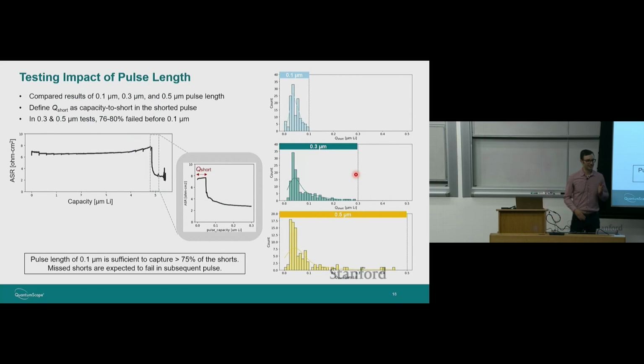I'll do one quick digression here into ensuring that we've tested the validity of our test. One question that we've gotten sometimes is, are you applying this current density for a long enough time to cause a failure, if there is going to be a failure, or are we just doing the test too quickly? Imagine you bend a material very quickly, it'll break at some point. Will that break happen at an earlier or later point than if you bend the material slowly? So that's what we wanted to validate for ourselves, to make sure we're performing a valid test. If we applied current for a longer or shorter time, would this failure population differ?